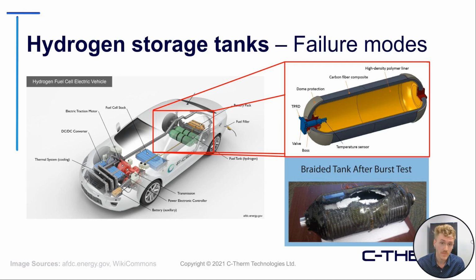These have to undergo multiple cyclic pressurization cycles, and therefore they're extremely tested for their burst time, their burst pressure. And as we're trying to extend the range of these vehicles, we want to have more and more hydrogen that's available for these tanks. So we have to design materials that are more elastic, that are able to be stronger to hold this pressure in. A failure of one of these tanks would result in either a fire for the car, which is obviously not a great thing, or just dramatic loss of the vehicle completely through loss of fuel. So it's very important for us to get this right.